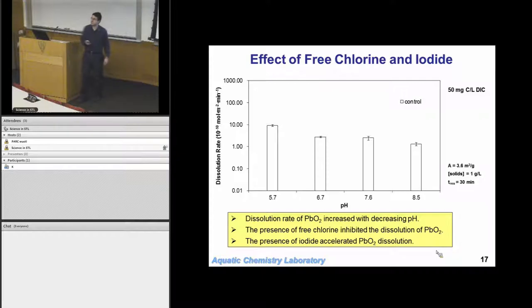So we also did some experiments to look and see, well, how quickly does this lead 4 oxide, this PbO2, dissolve as a function of water chemistry? So we're going to look at this at 4 different pH values, from 5.7 up to 8.5. This is our control. This is dissolution rate of lead in water at these pHs with some inorganic carbon there. And I'll point out that this is a log scale. If you're new to science, always look at your axes. So this is 10 times as fast as this, another 10 times fast all the way on up.